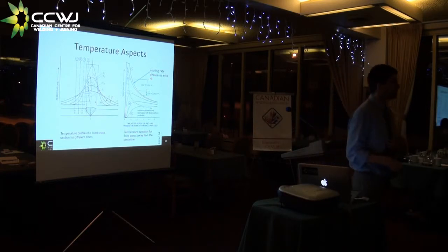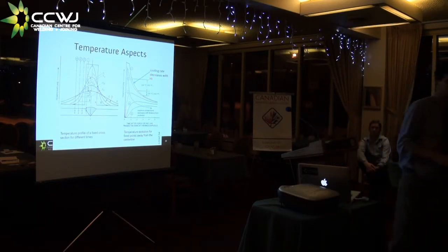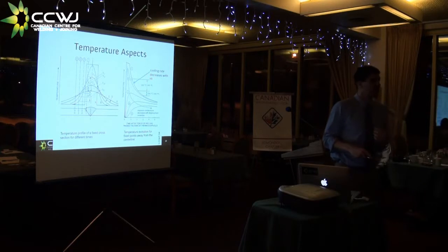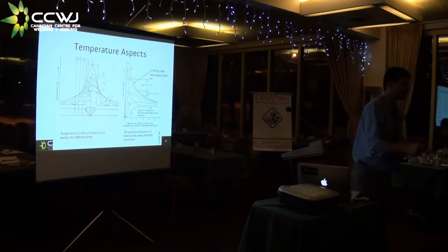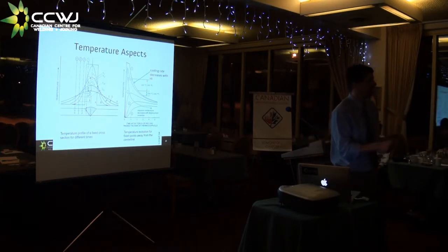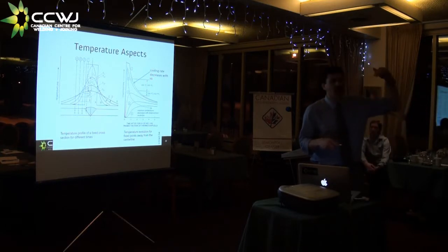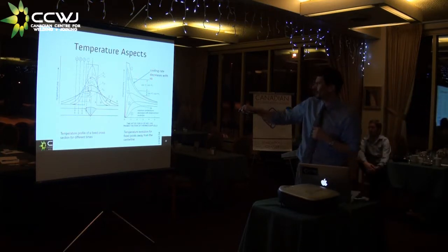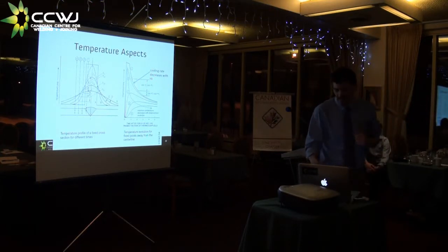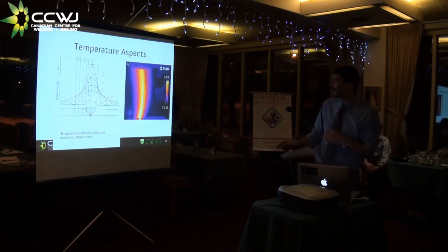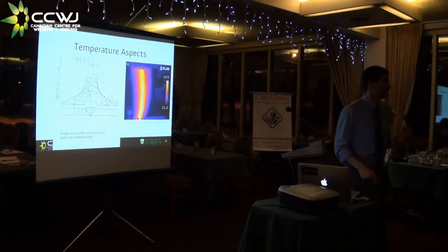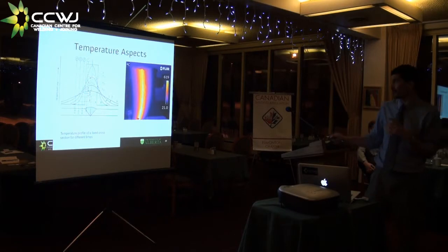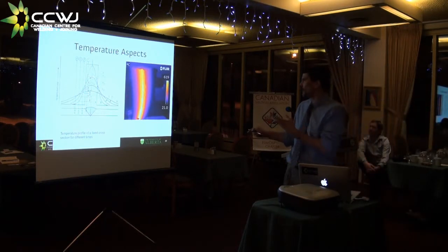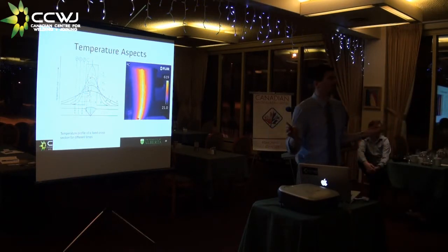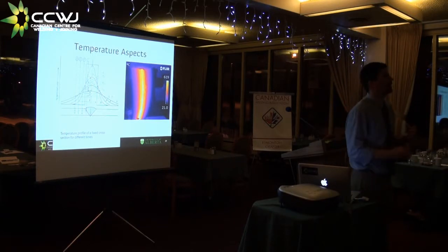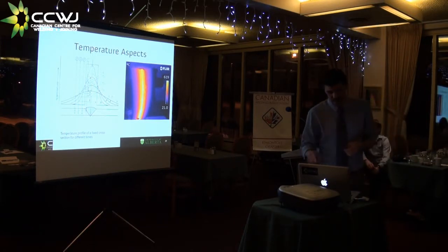This is what we measure with thermocouples. And actually, in the lab, and you can ask Steve, sometimes we try to put the thermocouple inside the weld pool to measure from the hottest possible point down, and measure the cooling rate. If all goes right, one of the toys we don't have yet, but I'm working on, is a thermal camera, where you get to see temperatures on the plate and the gradients and the evolution with time. So let's see.